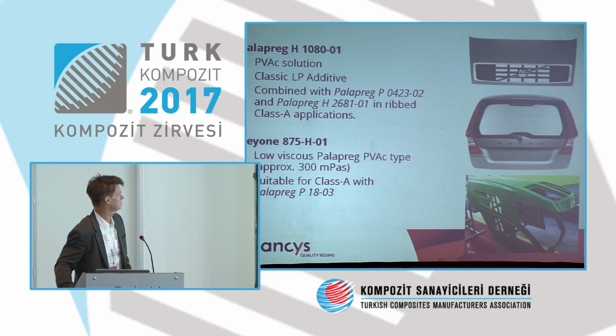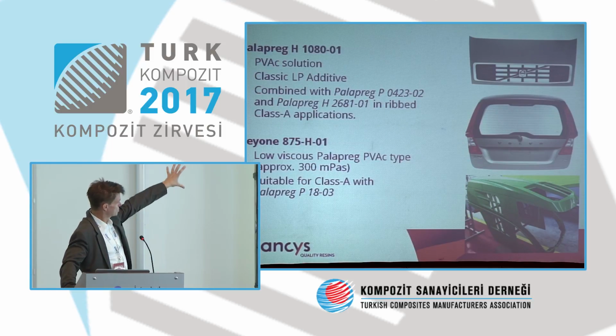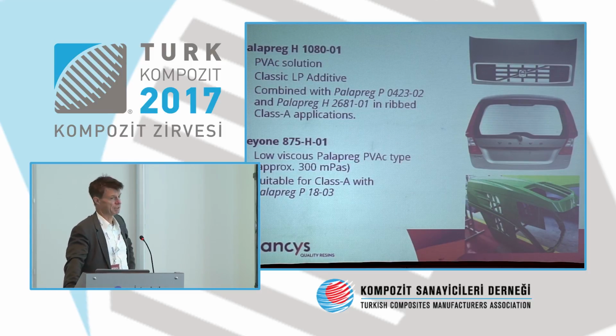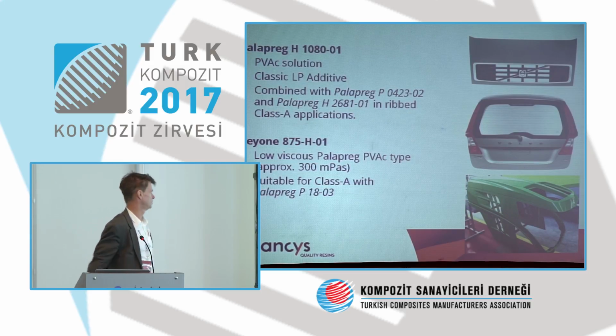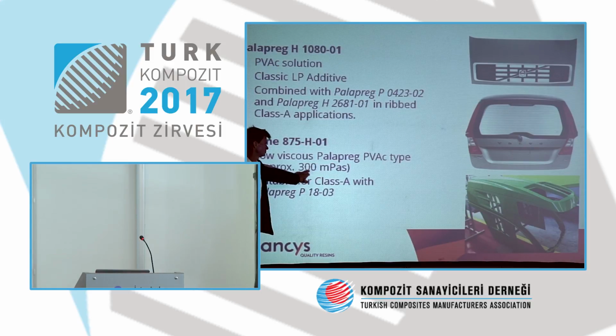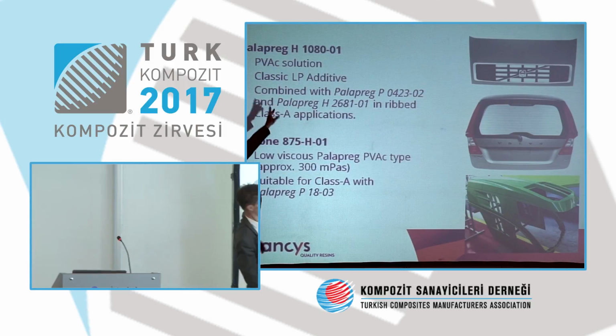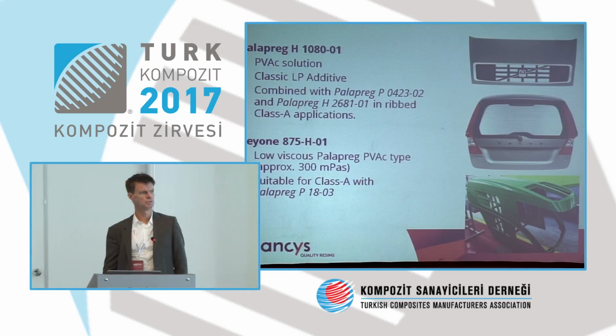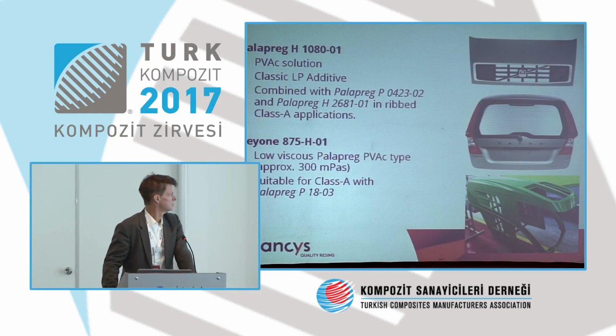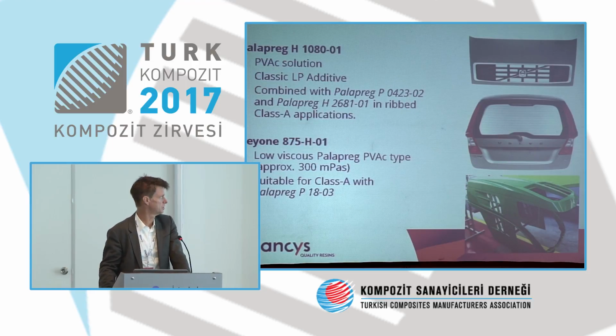Other parts you can look at, now we are coming to PVAC solution, for example. Two different components. One is the higher viscosity. It's, let's say, the one which was developed many, many years back. And the new generation is H875, which gives you a viscosity of approximately 300. Compared to this, about 4,500. So you're more than 15 times lower, which enables you to play around with your formulation, to add more filler, to lower the cost on the formulation.